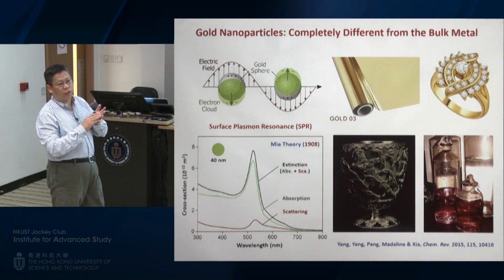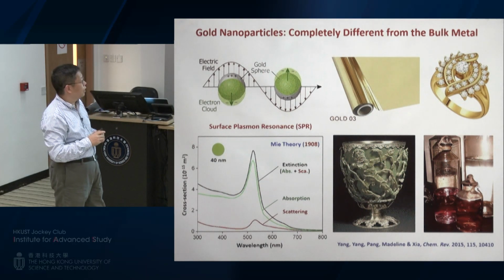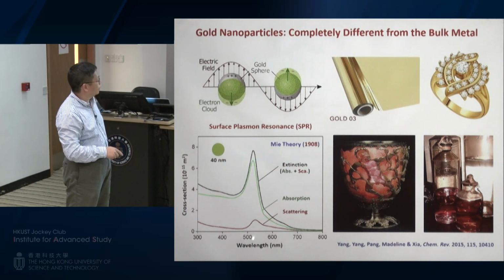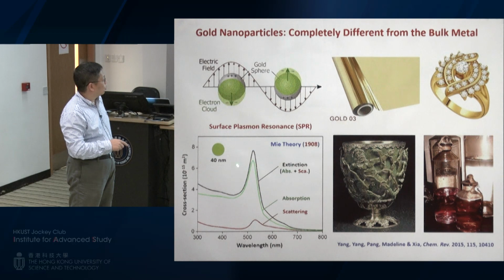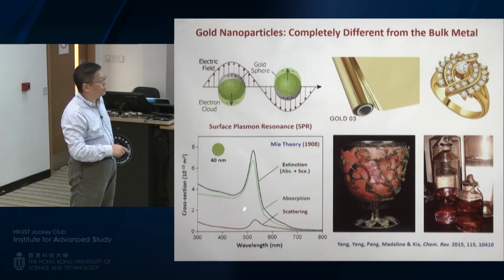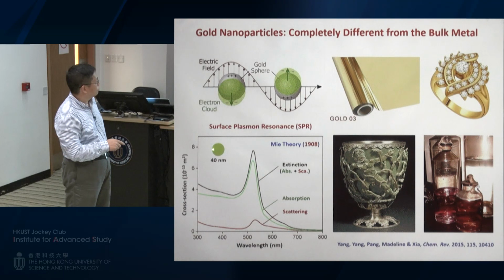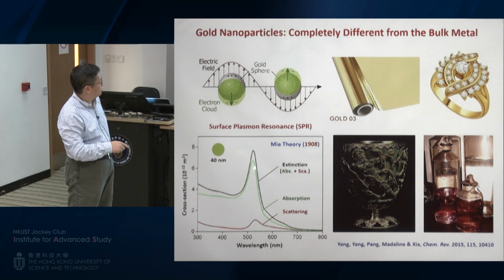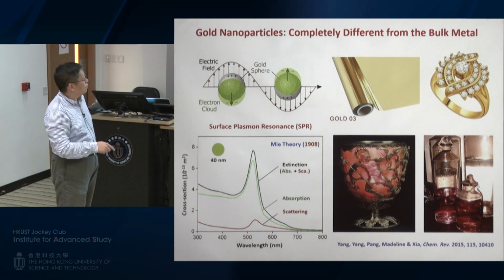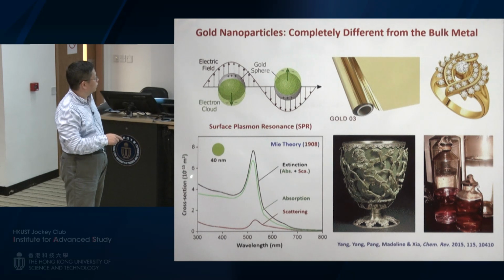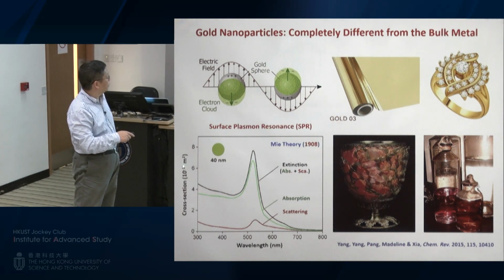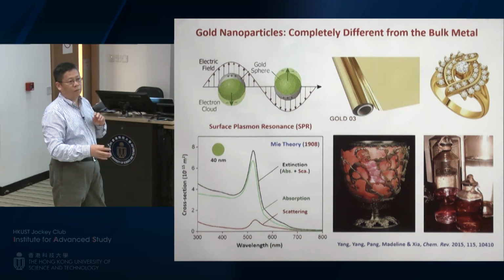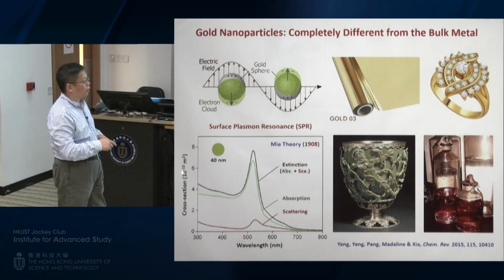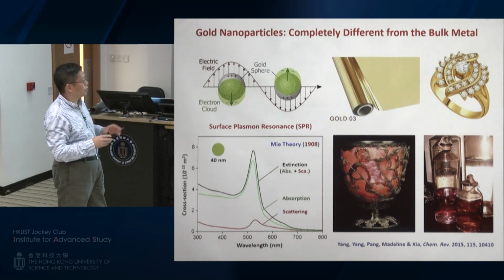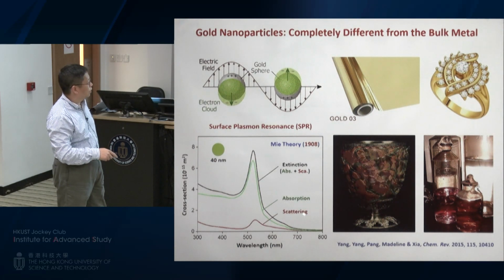Depending on the size, shape, composition and many different parameters, this surface plasmon resonance can occur at different wavelengths or frequencies. For a gold sphere about 40 nanometers in diameter, the resonant peak is about 520 nanometers. Absorption dominates for smaller particles, and in this case it's about 10 times stronger than the scattering component. But both are much stronger compared to molecular species, with a cross section of about 10 to the minus 15 square meters. Even the best organic chromophores you can make are about 1 million times weaker. So you can see the particle is very powerful in scattering and absorbing light.